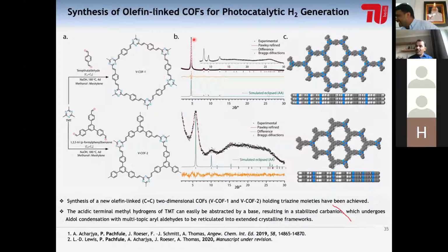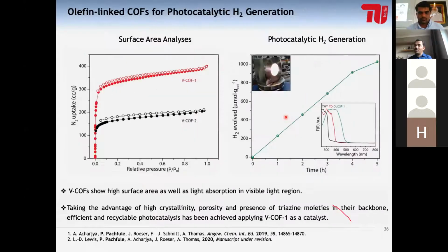And these materials have very good crystallinity. They exactly match the simulated PXRD pattern. They have a pore size of 1.9 nanometers, which is pretty nice for any application. Someone might ask what is happening with the porosity of this material. These materials have very high surface area, beyond 1500 square meters per gram. That means 1 gram of the material has a surface area as high as a tennis court, which is pretty impressive to do any kind of chemistry inside.